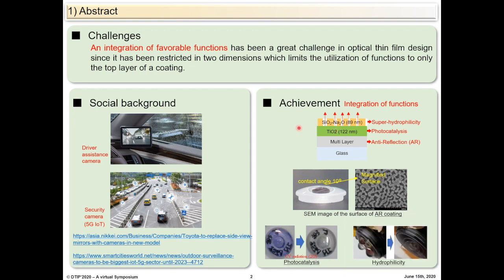In this talk, a superhydrophilic SiO2 Na2O layer on the surface and an underlying photocatalytic TiO2 layer are connected via nanostructured through-holes by reactive dry etching technique. By this three-dimensional configuration, we could achieve three functions altogether on an AR coating. This is a confirmation of photocatalysis by methylene blue ink and UV light, a comparison between normal AR coating and superhydrophilic AR coating in this study.